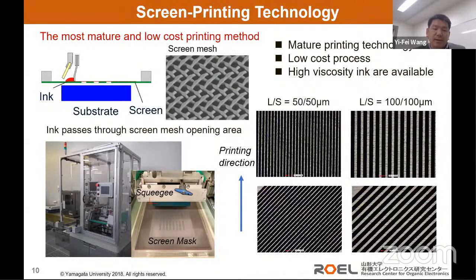And in here we show the illustration of the printing process of a screen printer. Ink was firstly placed on the screen mask, and then it was used with the squeegee and was coated through the open area of the screen mask, and then transferred to the substrate. And now already many screen printing machines exist, and by using this equipment, we can fabricate the sensors with quite high speed and also even at large scale. And the resolution of the screen printing is not as high as reverse offset printing, but still can reach the resolution of 50 micrometer. So it already can afford many requirements from the fabrication of sensors.